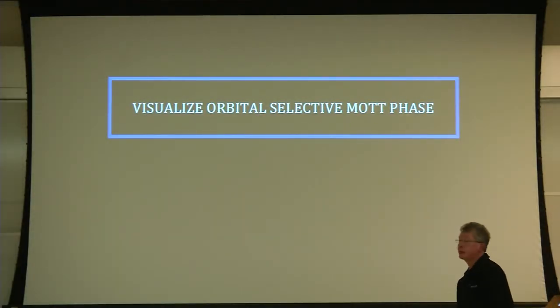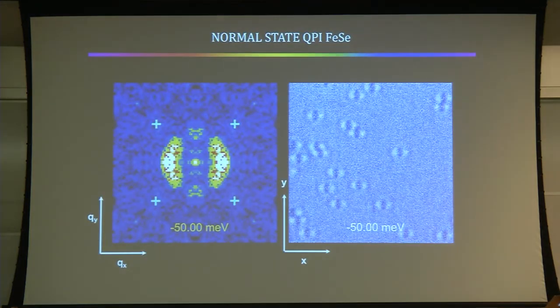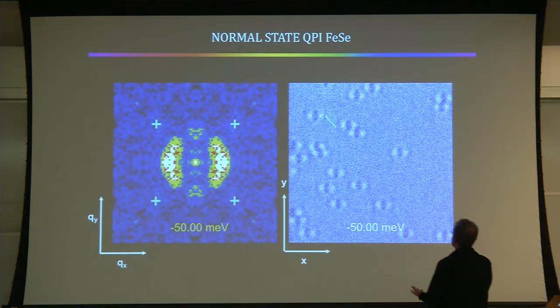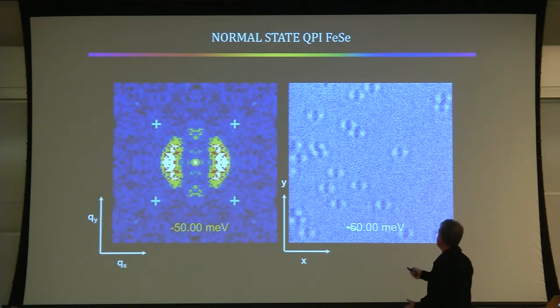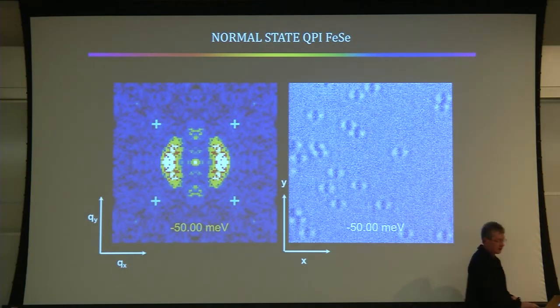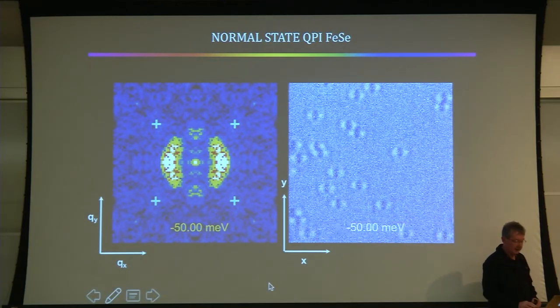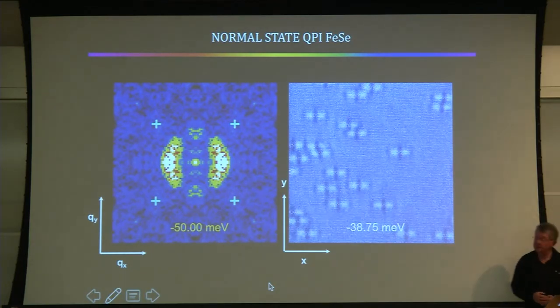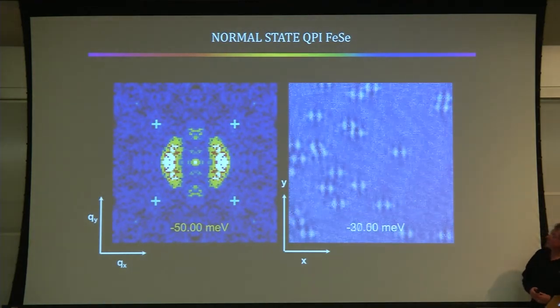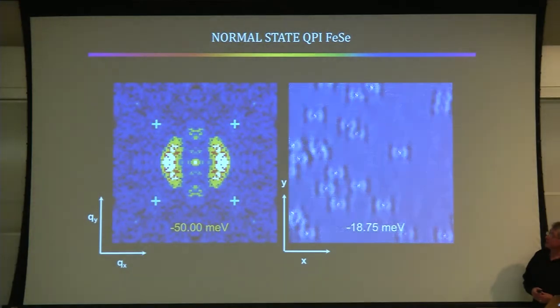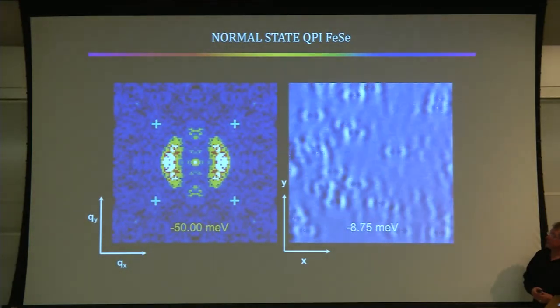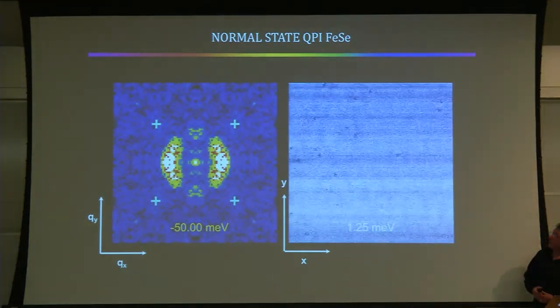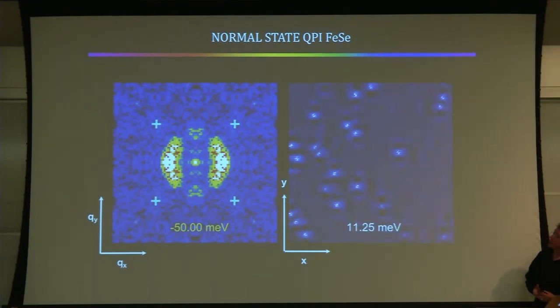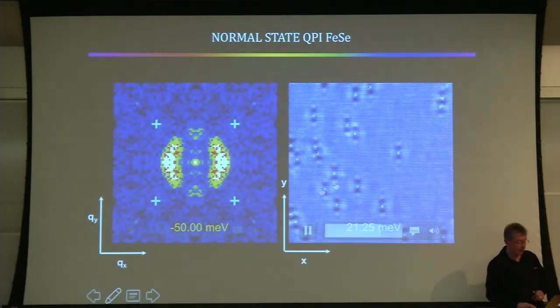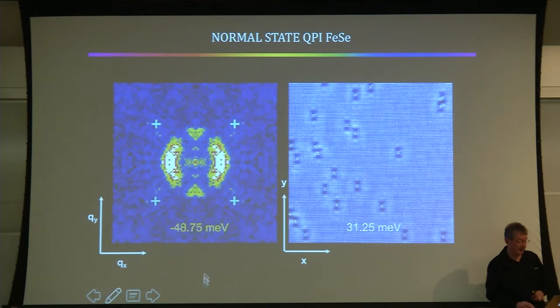Visualize the orbital selective Mott structure of the quasiparticles. So how can we do that? Well, we can see the quasiparticles. Now we're in the normal state. We just image the quasiparticles. Here they are, scattering off iron vacancies. And from these movies, you can get a great deal about the momentum space structure of the quasiparticle states in the system. And if I show you the Fourier transform, it's vividly anisotropic.